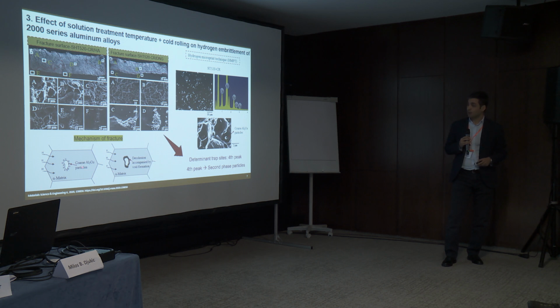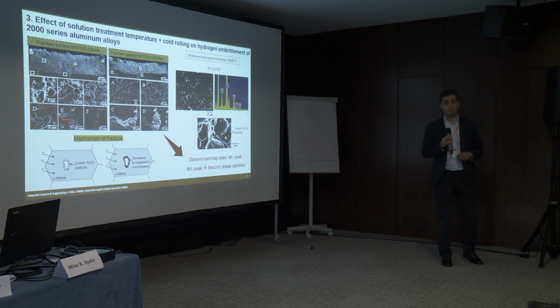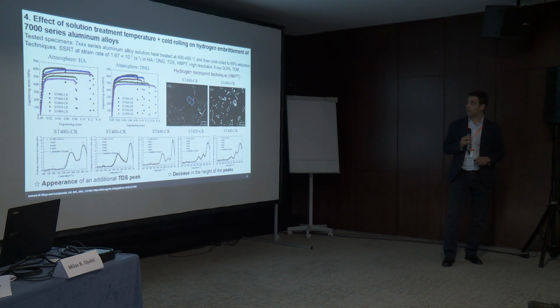It can be the separation around the second phase particles, and this eventually can be very important to see how the size of these particles, which can change with the solution treatment temperature, can be effective. And then also we can say that the TDS peak, as I told you, the second phase particles can be a very determinant factor here.